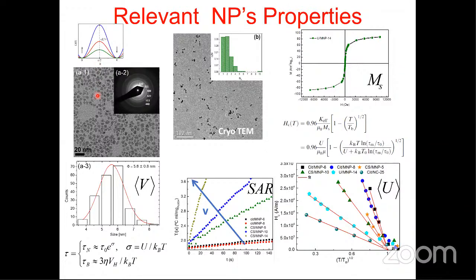We cannot manage, for instance, dipolar interaction. We cannot manage aggregation. Here is a very nice cryo-TEM image that shows this colloid, where we see a node that has already some aggregation. So we can go through them and see which is the mean value. We can measure SAR, we can measure saturation magnetization, and we can do some nice experiments of coercive field against temperature at low temperature.